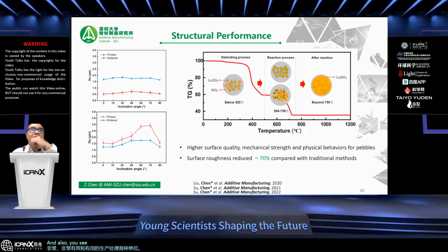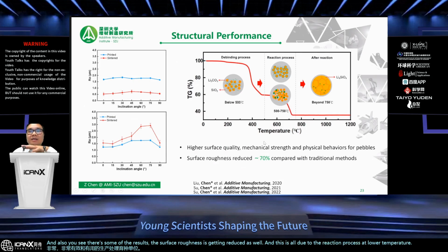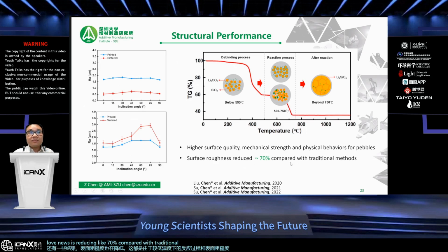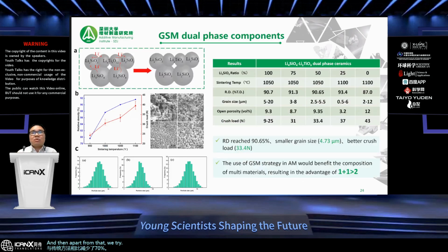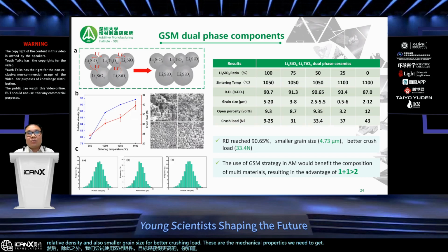And also, you see there are some results. The surface roughness is getting reduced as well, and this is all due to the reaction process at lower temperature. The surface roughness is reduced by like 70% compared with traditional methods. Then apart from that, we try the dual phase components. The aim is to get higher relative density and also smaller grain size for better crushing load. These are the mechanical properties we need to get, and we aim for 1+1 much larger than 2. So this is called dual phase components, including the titanium and the silica as well.